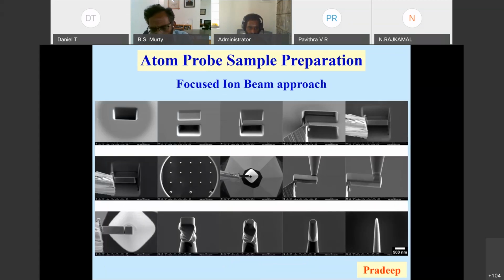FIB, people call it as. FIB is basically an SEM. Okay, the only thing is we call such an SEM as a dual beam microscope, where you have one beam which is an electron beam to see the sample, another beam which is an ion beam to cut the sample. It's basically a kind of a milling machine or a drilling machine, if you can call so. So you can take a sample and cut the sample using a focused ion in such a way that from a flat plate-like sample, you can cut from both sides so that you have a small portion here which is of interest, and cut that portion.